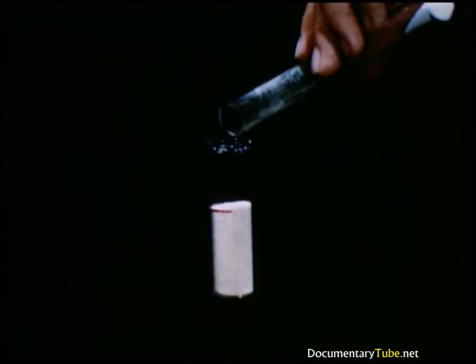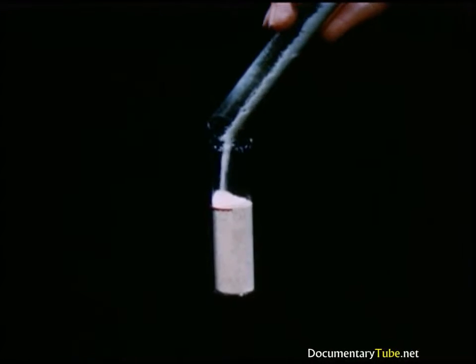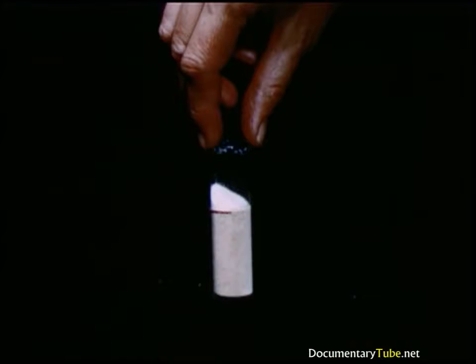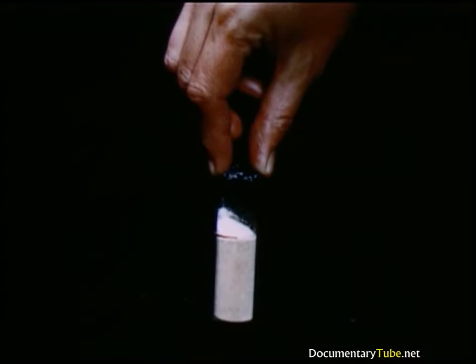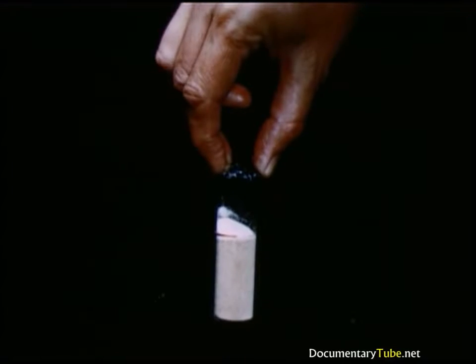bonding mixture. The vaporized silica is so fine that a considerable quantity may be dissolved in the magnesium oxide without increasing the initial volume. Likewise, this mixture dissolves in the aggregates, making the compressed brick at its maximum density. Firing the closely compacted bond particles causes them to form the ceramic bond, magnesium orthosilicate, by a solid phase reaction.